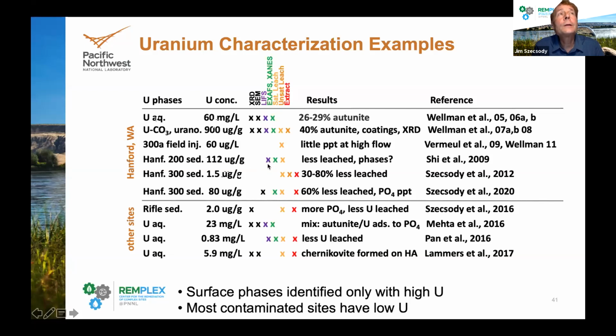In this study, they had about 112 microgram per gram uranium. They did try to do some surface phase analysis, and they were right on the edge of being able to identify what the surface phases were. So you need a little bit more than that to identify what the surface phase is. That's the kind of balance: it'd be nice if you could do it all, have leach experiments and identify surface phases, but because of the detection limits, there are limitations of what you can do at field sites.